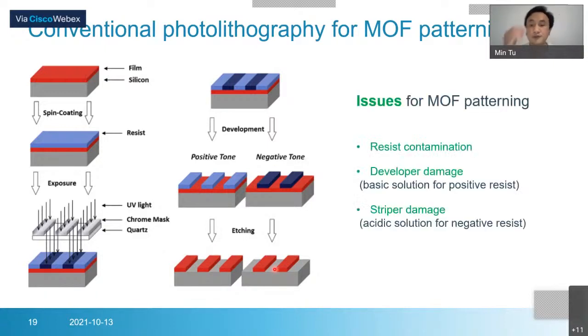But when we use photolithography for MOF film patterning, we have the problem of, first, resist contamination. We know MOFs are highly porous structures, so the components of the photoresist can penetrate into the MOF film and contaminate it. And also, most MOFs are base sensitive or acid sensitive. So the developer, basically a basic solution, can damage the MOF, and for a negative resist the stripper is an acidic solution, which can also damage the MOF film. So conventional photolithography has problems for MOF patterning.